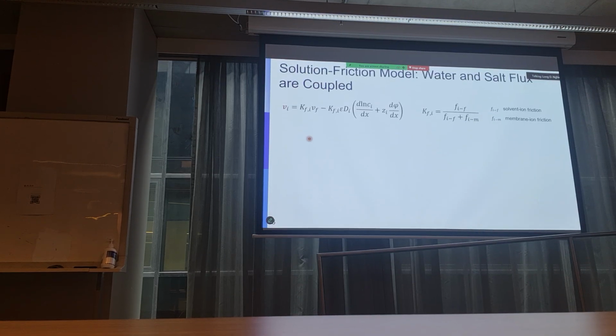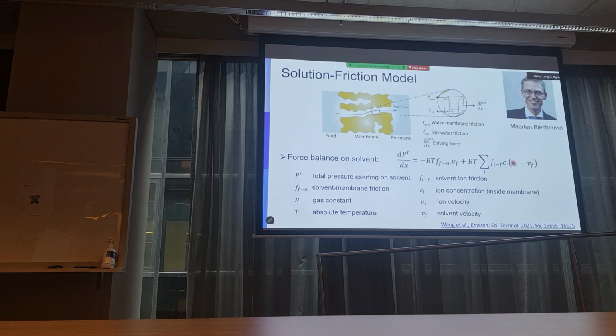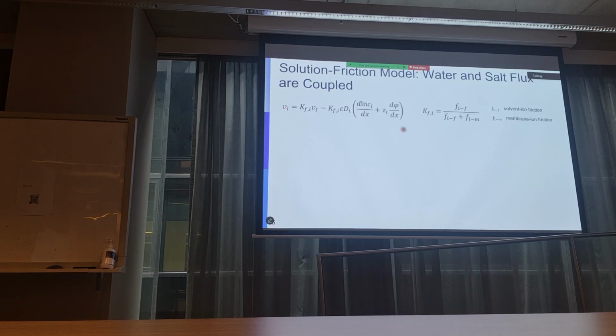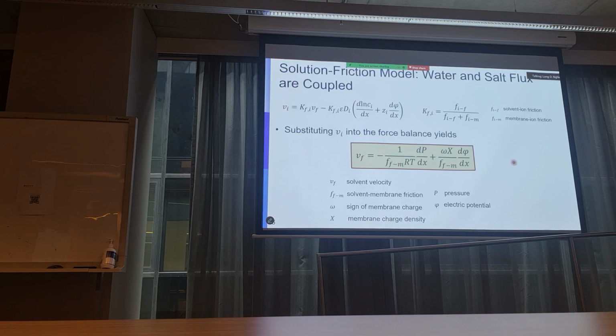And you can now write the expression for the velocity of the ions. We can use more like an extended Nernst-Planck equation for the velocity of the ions, and define a friction coefficient as described in the paper, and plug this V_i in here. And when you simplify, going through each step, you get this kind of behavior.